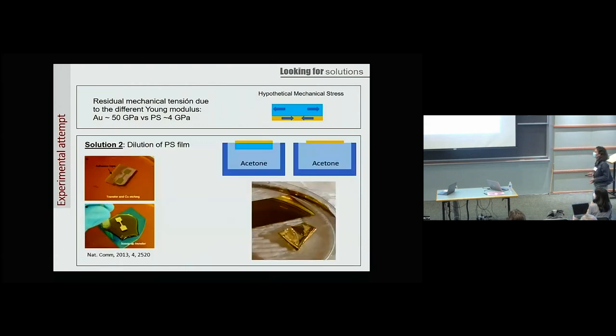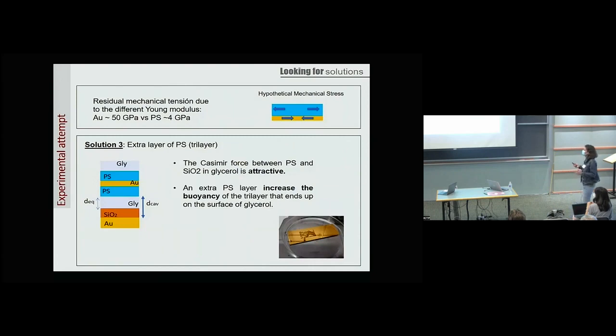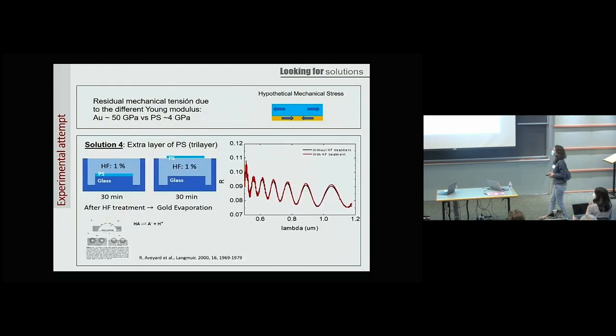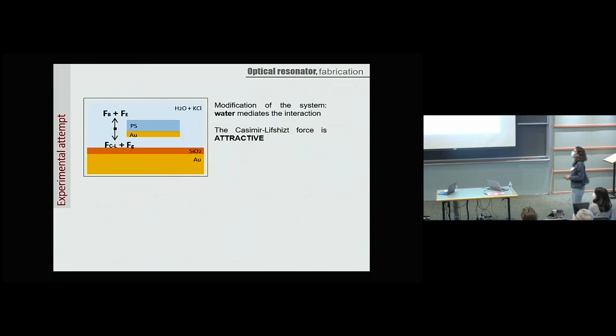Still rolling up. We tried acetone to maybe just remove the polystyrene, but it didn't work out. Okay, let's try a tri-layer of polystyrene. So I have some mechanical tension here, I will have it also here, so maybe it gets flat. But of course, now the force is attractive between these two materials, and because of buoyancy, it was going to float. Then we also considered HF. Because of the way we deposited the polystyrene film, then immersed it into water at a certain angle so that it could be released, maybe something was going on in that procedure, so we tried a different one with HF that is going to eat the glass. So you can do this differently, but everything was basically the same. We changed our model or design.